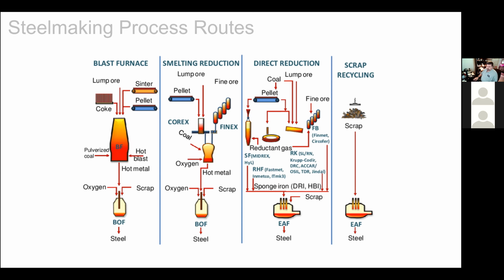So what this allows us to do is, depending on what the chemistry of our hot metal is, we can make a charge calculation and add scrap. And this scrap helps to soak up all the extra energy that we generate in here as we reduce the carbon and the silicon content of the hot metal and produce steel. So typically in North America, we tend to charge 25 to 30% scrap because of our hot metal chemistry. In some places like China, they were typically around 10, and recently they've increased to about 15% scrap. So there is some steel scrap that gets consumed in the integrated steel process.